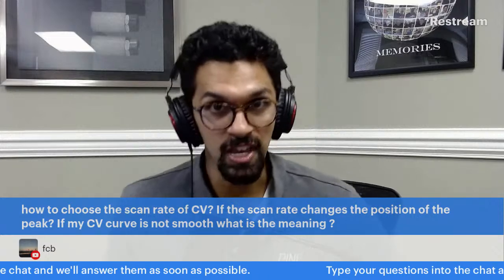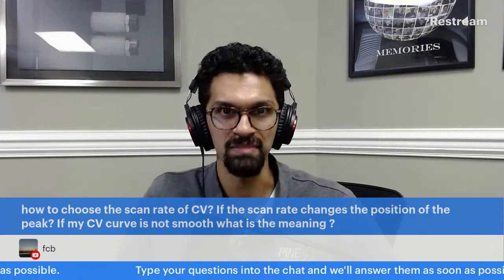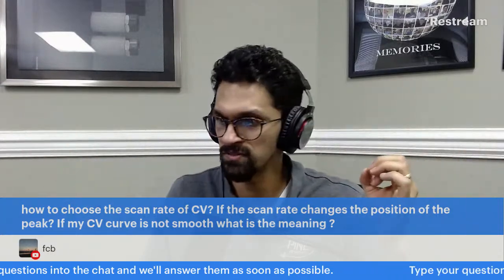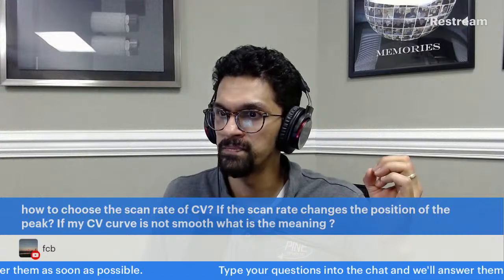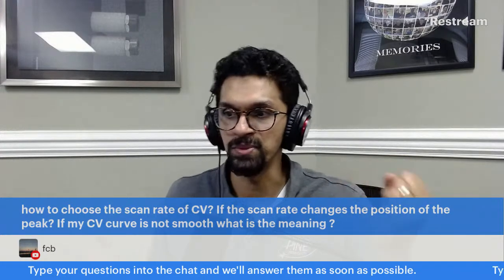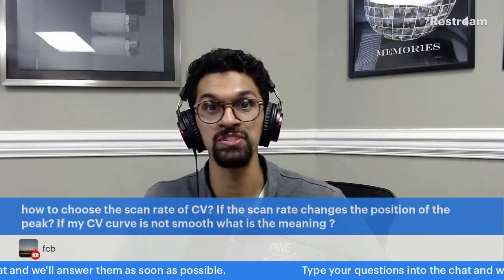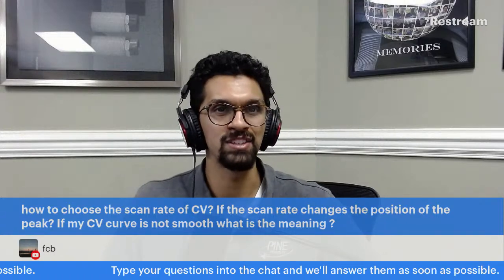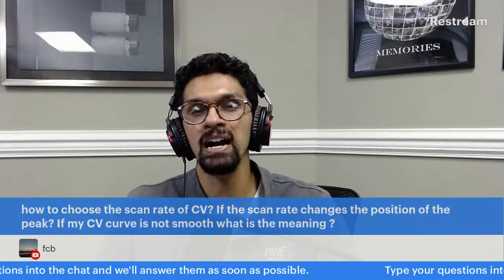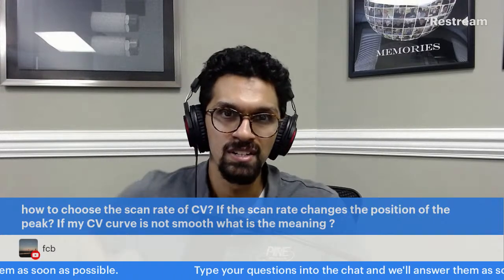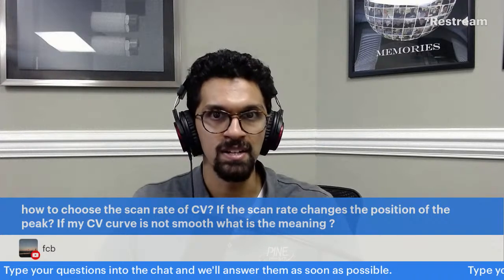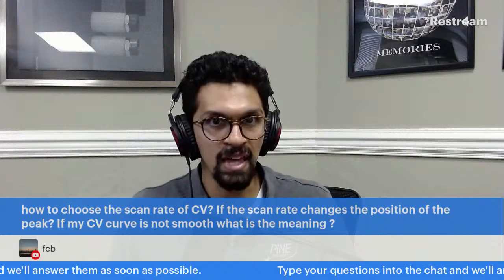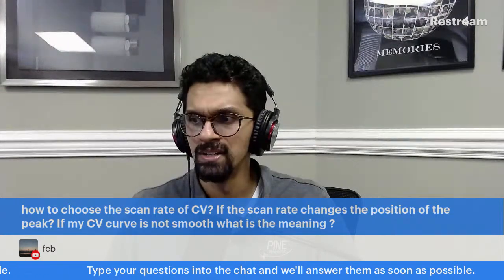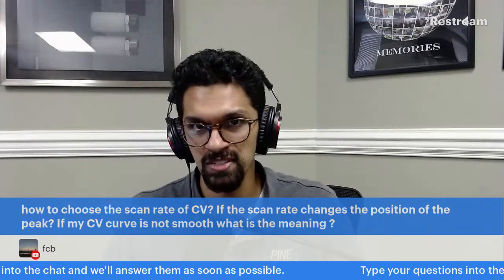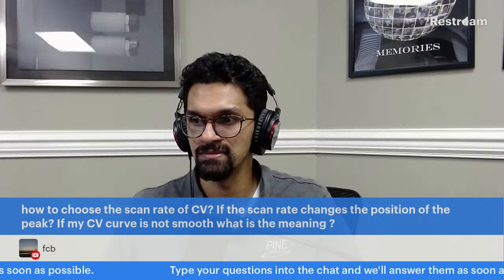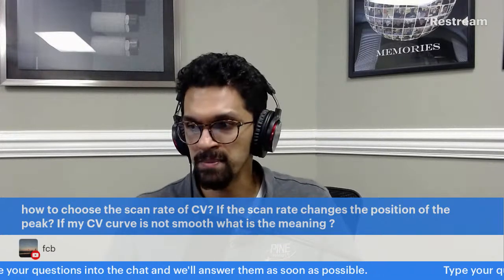Most people will choose a scan rate of, say, 100 millivolts per second. That's the standard starting scan rate for most of these things. And then you might go faster, or you might go slower. It depends on what you're looking for. But if the scan rate is changing the position of your peak, you most likely have either a kinetic issue, but most likely an uncompensated solution resistance issue. The peak position should not, in principle, change as a function of scan rate. Of course, if you have slow kinetics, it's going to change. But if it's supposed to have fast kinetics, you may have uncompensated solution resistance. So I think you probably need to check whether you have any uncompensated solution resistance.